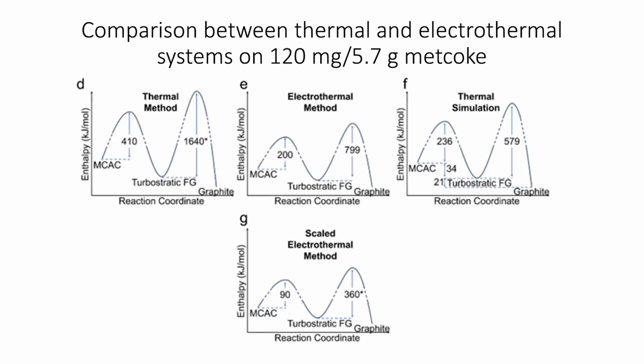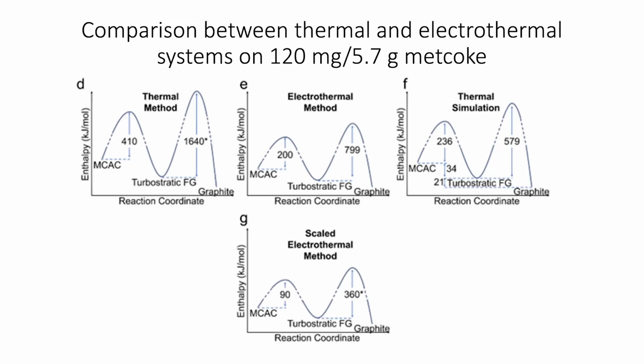So what we can show here is the different activation energies. You take metallurgical coke activated carbon, and if you do it thermally, you have to put in 410 kilojoules per mole to get it to go to turbostratic flash graphene. Graphene is more stable than amorphous carbon, so you're going down, so delta H is negative, though you had a high activation energy. And then from turbostratic to graphite, to where you really get a graphitic material, you have to now order these different layers. You have to pump in a lot more energy, 1640 kilojoules per mole. Well, on the same amount of material, here you're putting in half the amount of energy. So you've really lowered the activation energies by driving a current through the material. And here's our simulations.